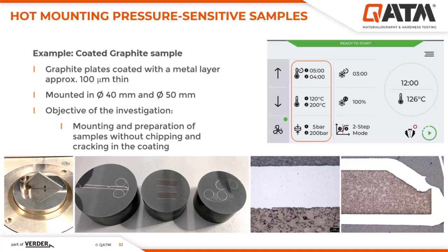On the left, you can see a sample segment positioned in the mounting press using a sample holder. The samples were mounted in different sizes using the two-step mode. In the first step, the epoxy resin was melted for 5 minutes at 120 degrees and only low pressure of 5 bar chamber pressure. In the second stage, both the temperature and the pressure were increased to 200 degrees and 200 bar, and the sample was fully cured.